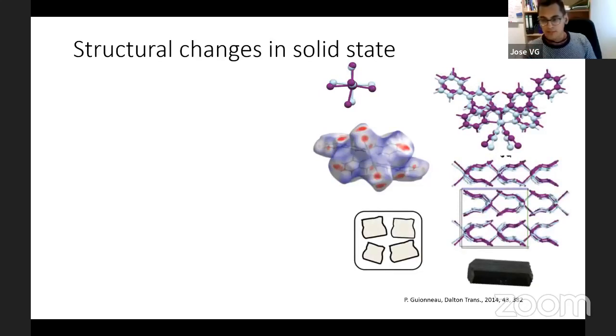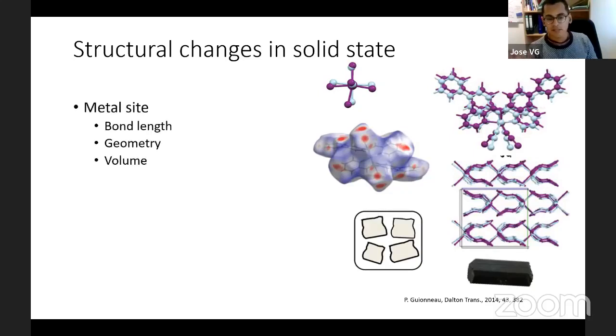So, as I said, in the pass from low spin to high spin, the first thing that happens is a bond length expansion between the metal and the ligands surrounding the metal. Why? Because we pass from a bonding orbital to a non-bonding orbital, and therefore there is a change in the metal size. As I say, with bond length expansion, the geometry of the pseudo-octahedral or octahedral can change to a more or less octahedral. And of course, because of the bond length expansion, there is an expansion in the volume of the coordination environment.